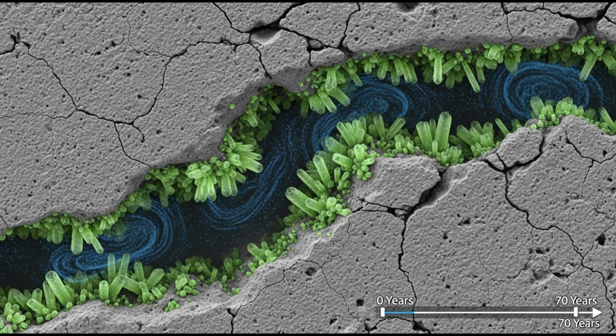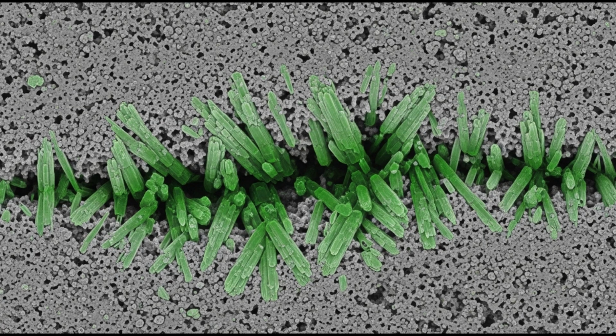Over decades and centuries, tobermorite crystals grow within the concrete matrix, particularly in voids and cracks. These crystals are highly stable and resistant to degradation. They interlock with the existing CSH gel. The result: the concrete becomes denser, stronger, and less permeable.